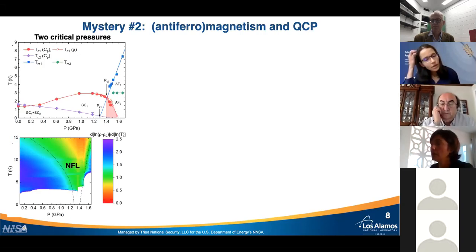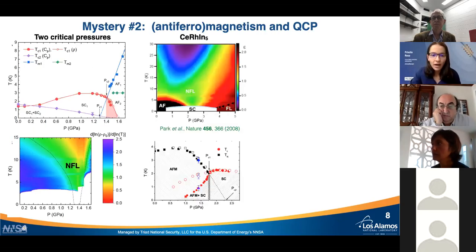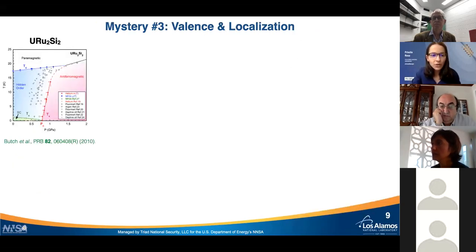Right. So again, going back to the fact that a lot of the groups, or all of the groups that studied this material under pressure got to the same conclusion in the phase diagram, that tells me that pressure inhomogeneity may not be playing a huge role here. In uranium ruthenium 2 silicon 2, here is actually all the phase diagrams from all these references with different pressure media.